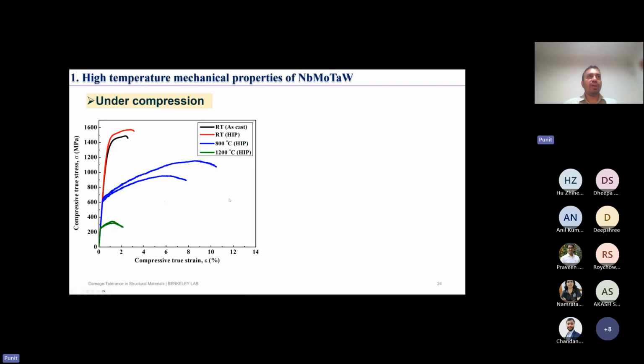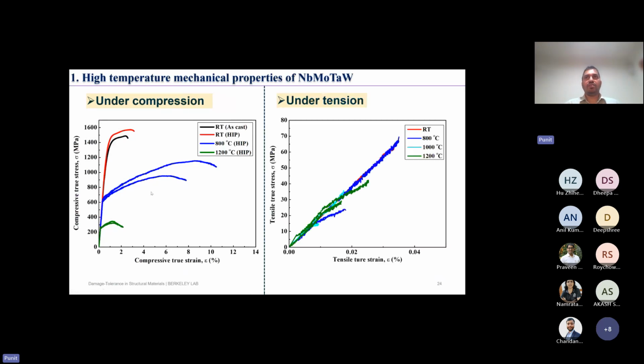So looking at compression behavior of this material, we see this material shows excellent strength retention up to 1200 degrees C, and there is significant plasticity also under compression, as it has been reported by several people. But if we look at the properties under tension, this is where we see the contrast. Now material fails before yielding at all temperatures, and the tensile true stress doesn't go even higher than 70 megapascal. And if you look at ductility under tension, it is less than 0.04%. So it's abysmal when you test this material under tension.